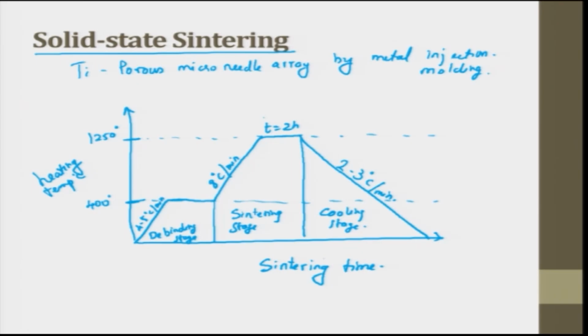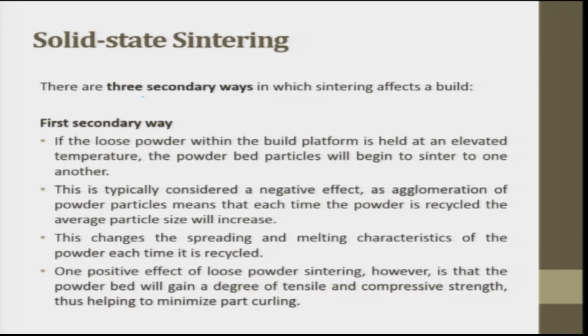After it is soaked for 2 hours, we remove the heat and allow it to fall down slowly. So it slowly cools down and you get whatever output you want. So typically this is how the sintering time and temperature plot looks for a particular application. There are 3 secondary ways in which sintering affects a build. The first secondary way: if the loose powder within the build platform is held at an elevated temperature, the powder bed particles will begin to sinter to one another.